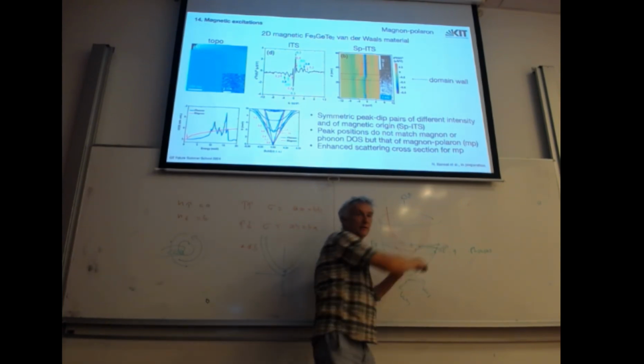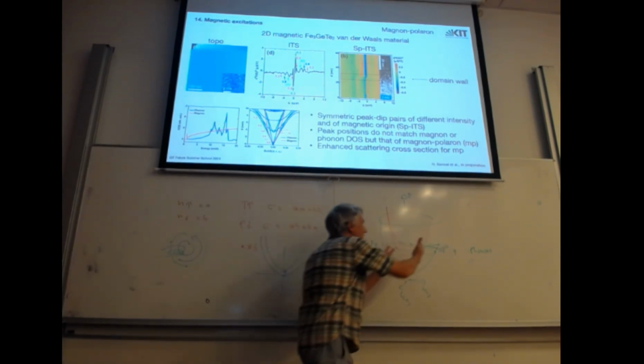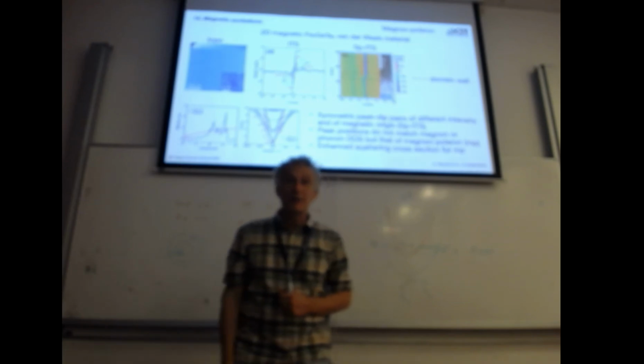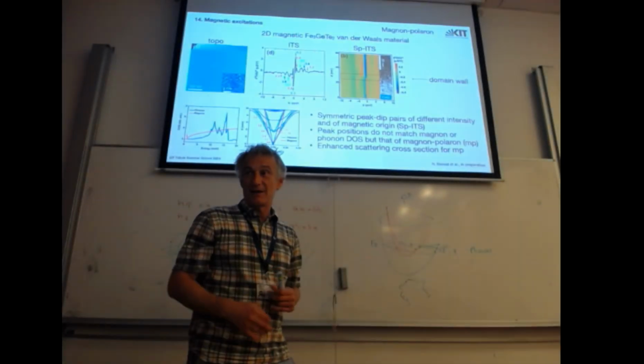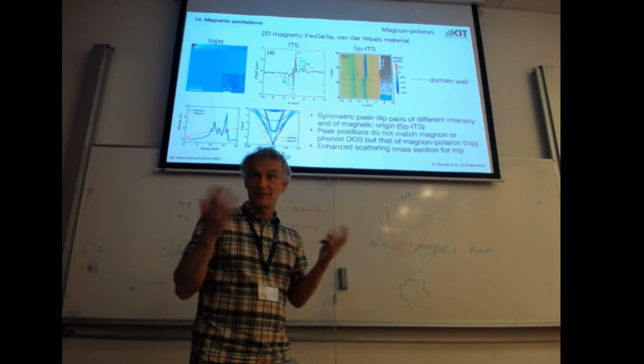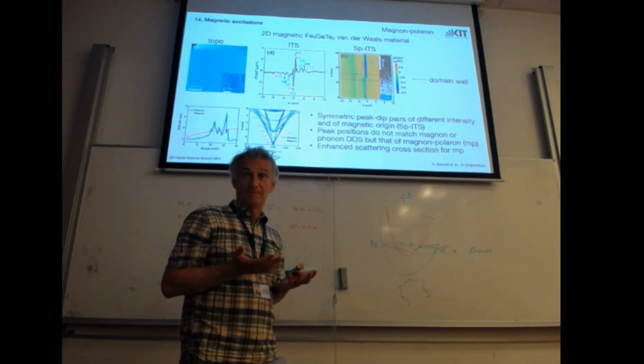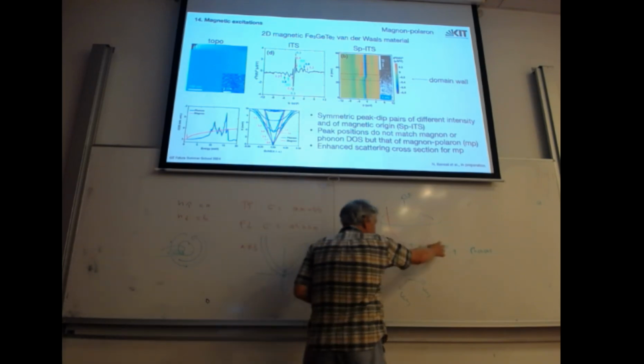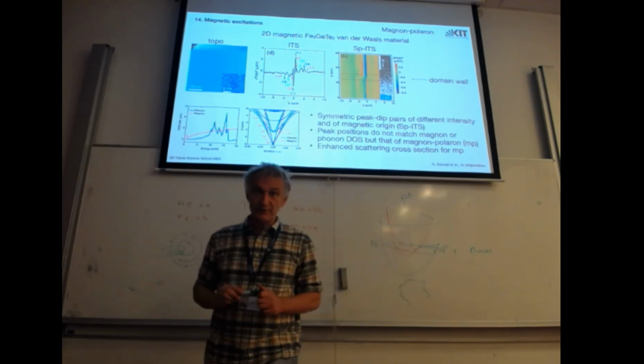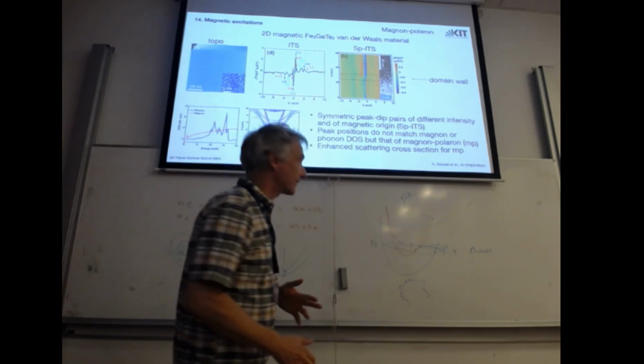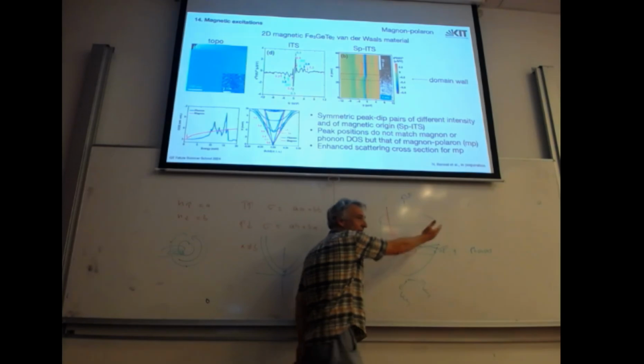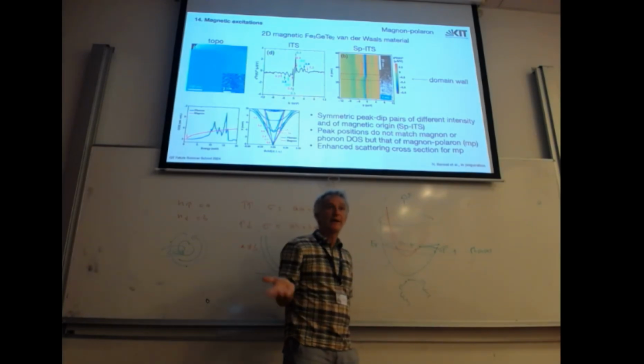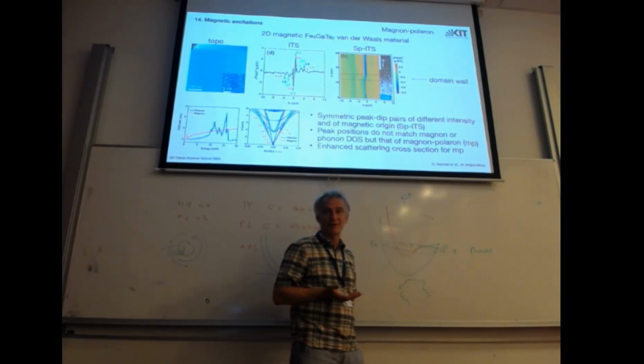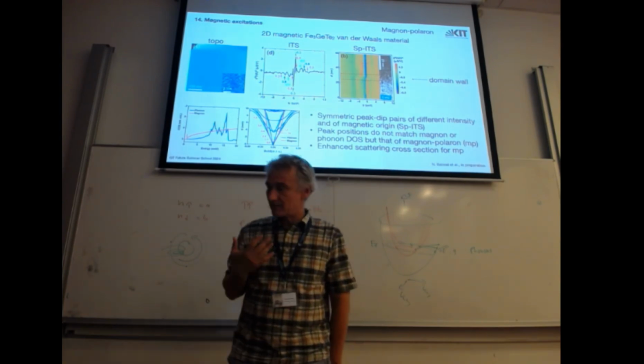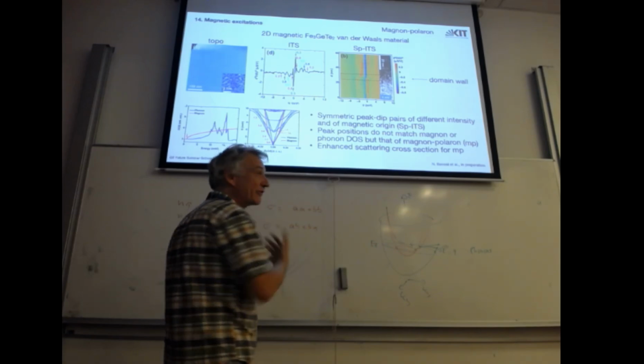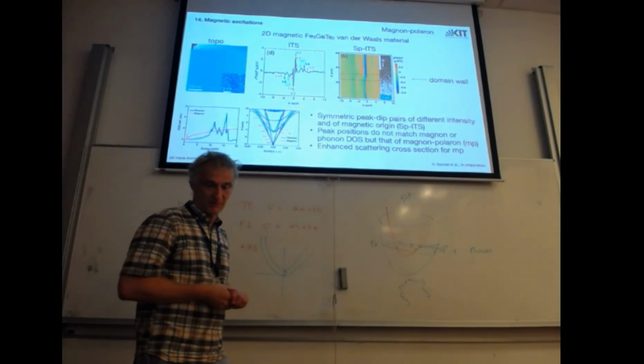The energy difference is arbitrary, but it will not be at Q equals 0. It's forbidden. And the low energy magnons have Q equals 0. So magnon scattering is not allowed in two dimensions. It's suppressed because I cannot at the same time fulfill energy conservation and momentum conservation. So I expect in my experiment to be blind for magnons. I should only see phonons.